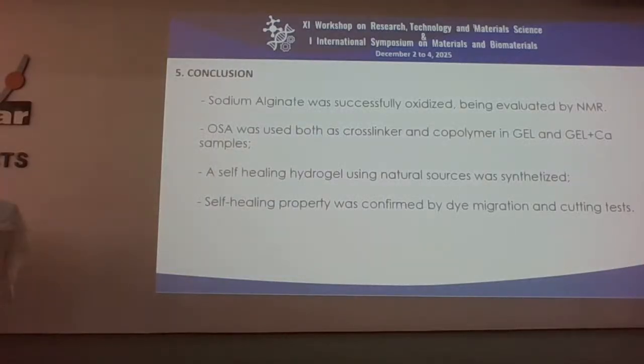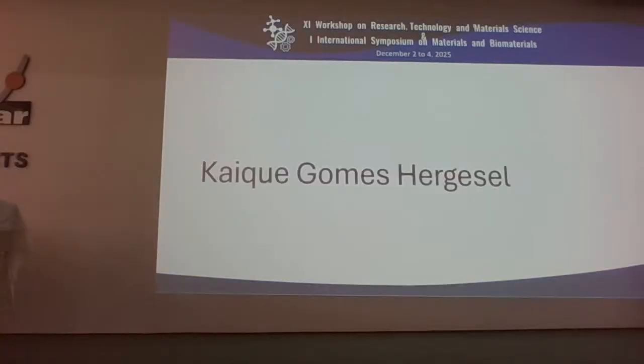So, in conclusion, sodium alginate was successfully oxidized and it was evaluated by NMR analysis. This material was then used both as a cross-linker and copolymer in the gel and calcium samples. And this self-healing hydrogel using natural sources could be successfully synthesized, and the self-healing property was confirmed by dye migration and cutting tests. Thank you for watching.